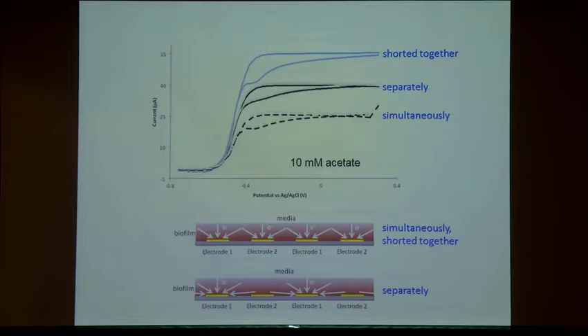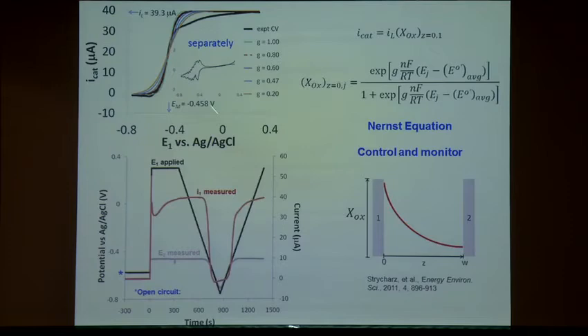So this is a catalytic voltammogram recorded separately, and the inset is the non-turnover voltammetry. And here's our Nernst equation. What we have done, and we've published this in the past, is we can actually fit the catalytic curve based on the Nernst equation. Essentially, the Nernst equation defines the oxidation state at the electrode surface. The biofilm sets up the oxidation state at every level in the biofilm, and that dictates the rate of electron transport to the electrode surface, and we can get the catalytic curve.